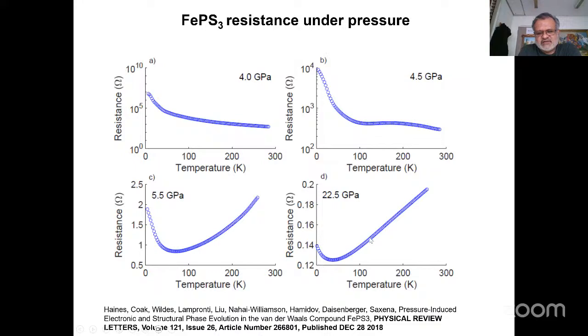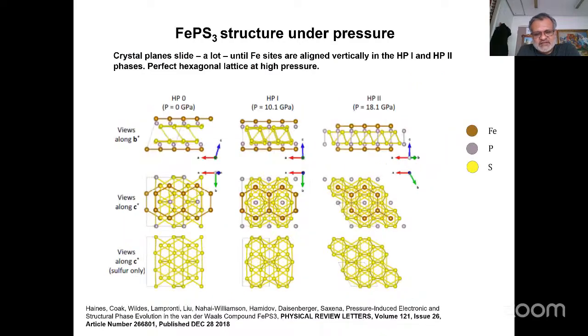But this resistivity here at 22 GPa looks very similar to that of high TC materials, for those who are familiar with that resistivity, linear in temperature up to very high temperatures. And then we want to understand what's happening crystallographically, so we can then track onto the spin and other parts of the band structure and Fermi surface in the material.